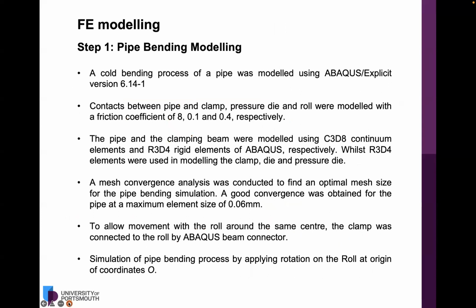So the first step of our work is to perform pipe bending modeling, where the cold bending process of a pipe was modeled using Abaqus explicit version 6.14-1. We introduced some parameters, such as the contact between pipe and clamp, pressure die, and roll, with friction coefficients of 0.8, 0.1, and 0.4 respectively. We use C3D8 continuum elements and R3D4 rigid elements of Abaqus to model the pipe and the clamping beam respectively. Meanwhile, the R3D4 elements were also used in the modeling of the clamp die and pressure die. We conducted a mesh convergence analysis where we found a good convergence for the pipe at a maximum element size of 0.06 millimeter.